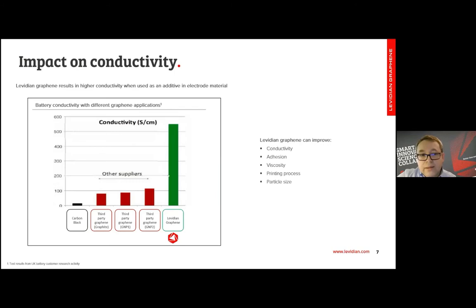We did look at other additives, comparing ourselves to graphite and other graphene nanoparticles available on the market, again originating from graphite. We were able to get quite superior performance in conductivity purely because the graphene that we produce is made bottom up, so we are designing the material with very high structural quality, but at the same time also high purity. Also, we are able to have the graphene in the absolute pure form without exposure to moisture or oxygen or any other species present in the air.